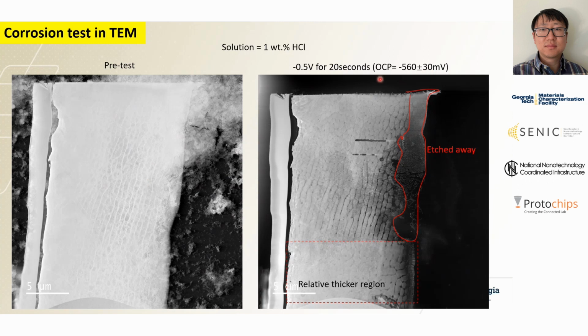So after we apply the voltage by overpotential of about 60 millivolts for just 20 seconds, clear corrosion happens on this material. The bottom side of this material is also the thinnest part and the most ion-implanted part, because we mill the sample with the ion beam at a certain angle. So this area was completely etched away, and this area is our region of interest.